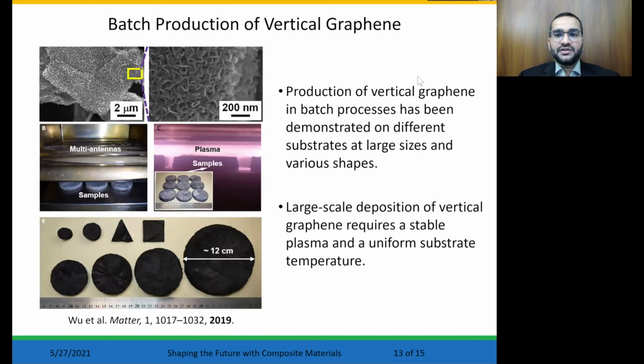Graphene nanopetals can also be deposited in larger scale using a batch process. This process accounts for most, if not all, published reports of vertical graphene or graphene nanopetals. The deposition is more controllable in this process, which can take from around 30 minutes to a few hours, depending on the plasma source and the process conditions, to produce vertical graphene in large area substrates, as shown in this work, which was reported by Wu et al.